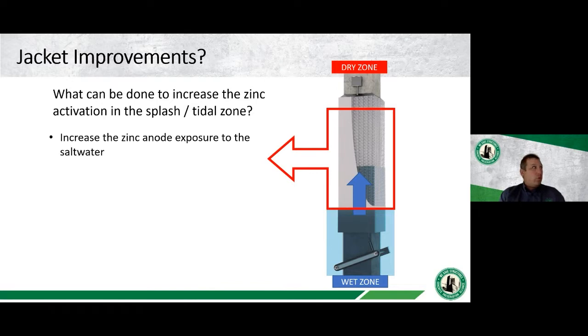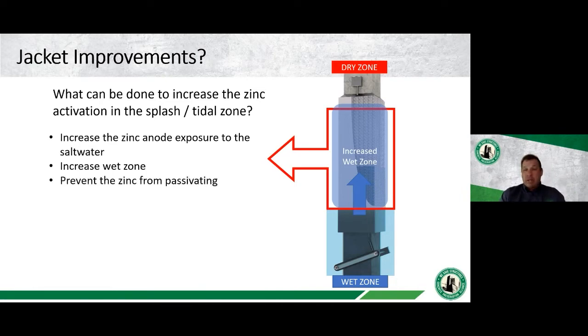Well, what we could do is increase the zinc anode exposure to salt water. And by doing this, we're basically increasing the wetting zone. And as we're increasing the wetting zone, we're just exposing our zinc to more activation. And potentially, we'd stop it from passivating. So if we're able to do this, we're going to increase our performance. And then as well, like you saw in the last picture, we can also increase our utilization of our zinc. It's not going to passivate, so we can get a lot more galvanic current.